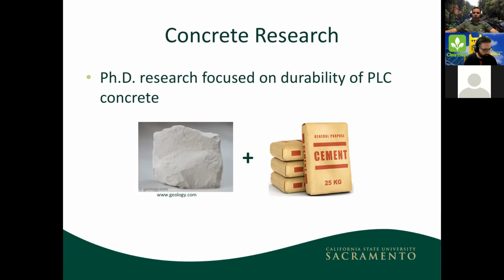And why would we do that? If we already have cement, why would we combine it with limestone? Well, the Europeans figured out that if you take up to about 15% limestone, you grind it up, you're diluting the cement, which is what's requiring the natural resources and the CO2 emissions. But you dilute it with this raw limestone, and it's not going to affect the engineering properties. It's not going to significantly affect the strength or the durability. But that 5 to 15% replacement of cement is going to reduce CO2 emissions by about the same amount. It's going to essentially mean we can now use less cement to get the same product that we were getting before.